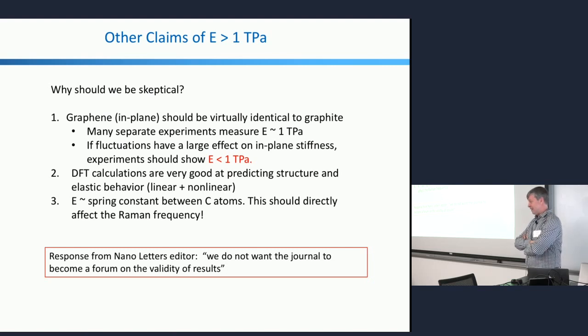But that would tell me that in bulk graphite there are no fluctuations, because you're constrained by the lattice. If you separate it out into single flakes, I would expect the Young's modulus of those flakes to be lower than 1 terapascal. And then if we somehow clamp them with these infinite mass defects, we get back up to 1 terapascal. That's what I would expect. But instead, they start at 1 and go up to 2, right? Again, I don't understand how that can be, if these fluctuations are so dominant.